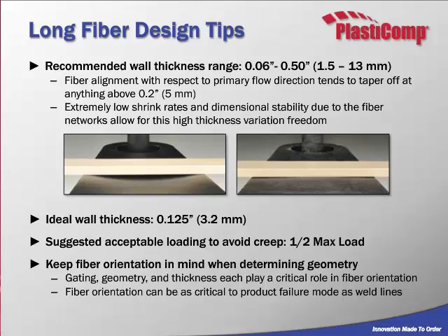Ideally, we would recommend an 1/8 inch. That's what our test bars are. Those are ASTM standards. We find a lot of strength there, and it starts slightly diminishing as you increase. From our findings, we're seeing that 200 thousandths is still a good thickness. You still have great fiber orientation there, and you still retain almost all of your strength. I wouldn't range higher than the 400 thousandths, personally, from what I've seen. When you're at 400 thousandths, you still have that fiber strength, you still have good orientation, but it is quite a bit diminished from the 200 thousandths.